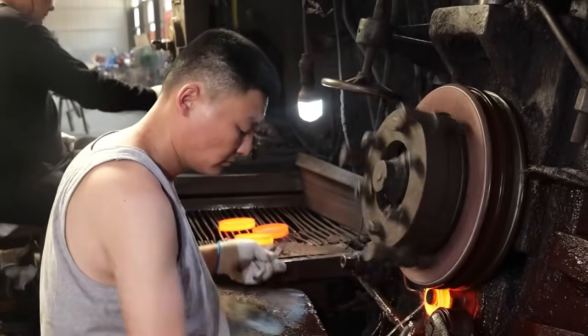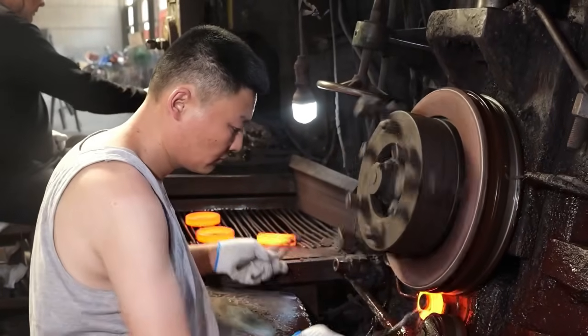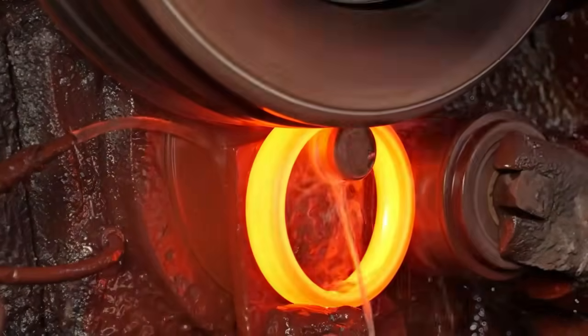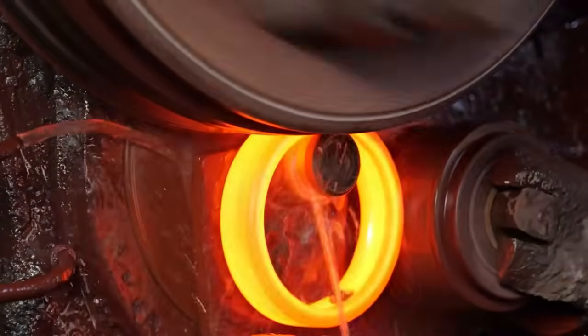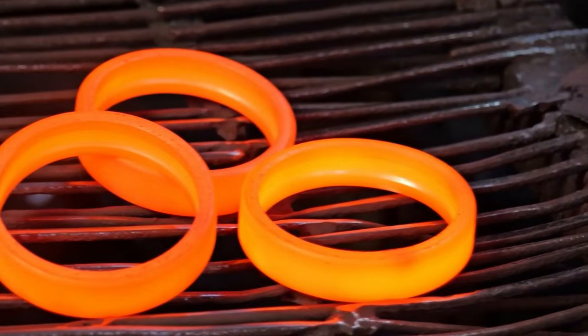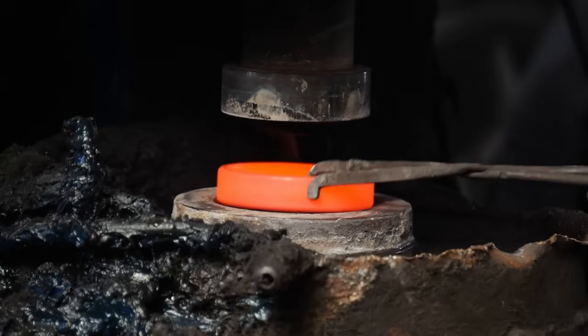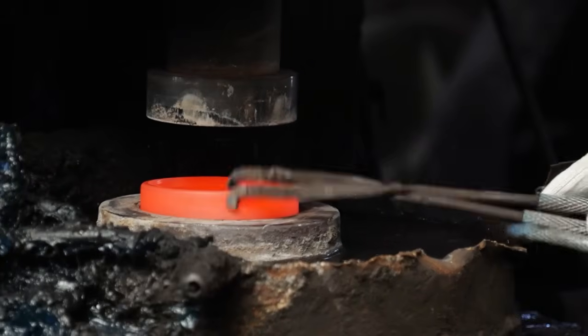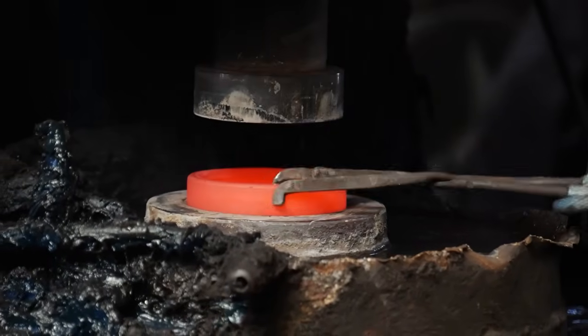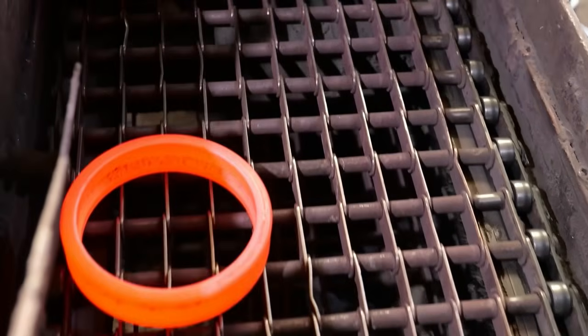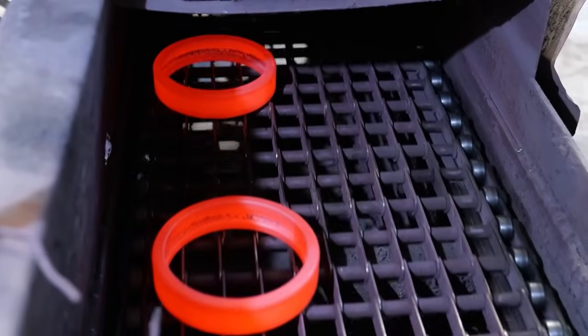From here, ring rolling and hole expansion fine-tune the size, getting it closer to what's needed for the specific type of bearing. Before machining with extreme precision, the rings are softened and stress-relieved through annealing, heated slowly to around 780 to 810 degrees Celsius, held for a couple of hours, and then cooled gradually to improve the metal structure.